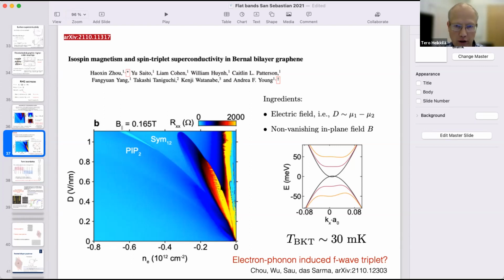Yes. So what we do is that we assume this local interaction, and then the estimates for the size of this local interaction from electron-phonon coupling are based on just projecting to the local one. But for example, Das Sarma in this paper and also earlier Fengcheng Wu for twisted bilayer graphene, they show that electron-phonon coupling can lead to a d-wave state, but it's actually subdominant in the sense that it has a higher energy than the s-wave state. And what Das Sarma shows is that both the singlet s-wave state and the triplet f-wave states are degenerate in zero magnetic field, and then at finite spin splitting field you favor the f-wave triplet.